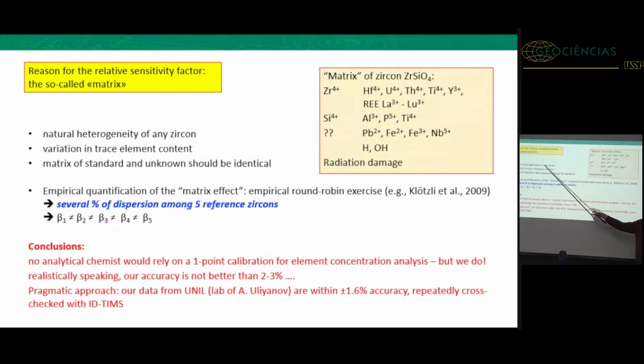So any zircon is naturally heterogeneous, and shows a variation in trace element content. Our standards, primary and secondary, and our unknown should be perfectly identical in terms of trace element concentrations, because otherwise you will have some lattice effects which are different between standard and unknown. It is theoretical. So we can actually quantify this matrix effect empirically.